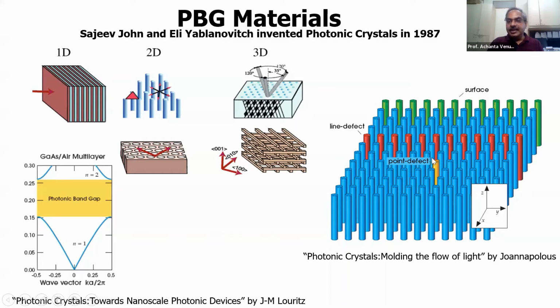Now, if you remove a rod, you can tune it in such a way that there is a defect mode. A defect is created because only one of the lattice sites is being modified. It's called a point defect. This point defect can be tuned to be within the photonic band gap region.